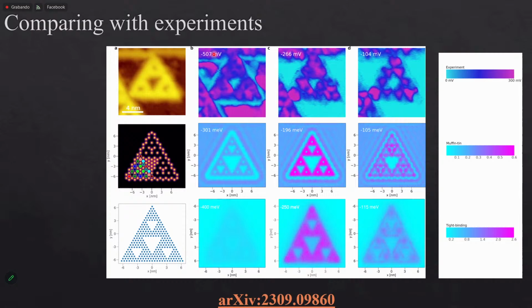Here you see that you have a state that's basically in the bulk. In this second row, I'm showing the results for the muffin-tin. This is how the potential looks, so you see that indeed you have this kind of region. Basically we are modeling the potentials where the electrons will not sit. And again, you see that you have occupation of states in the bulk. Actually, here it is not so high, but it gets a bit higher. And this is for the tight binding calculation.